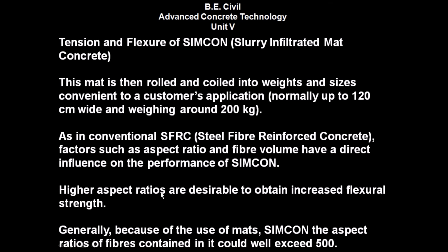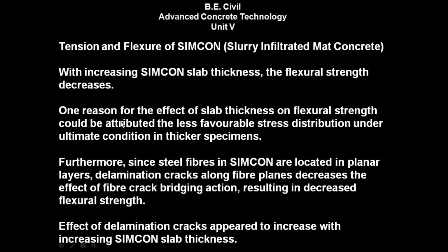Higher aspect ratios are desirable to obtain increased flexural strength. Generally, because of the use of mat in SIMCON, that is slurry infiltrated matte concrete, the aspect ratios of fibers contained in it could well exceed 500. With increase in SIMCON slab thickness, the flexural strength decreases.